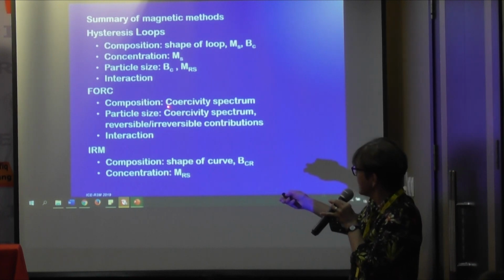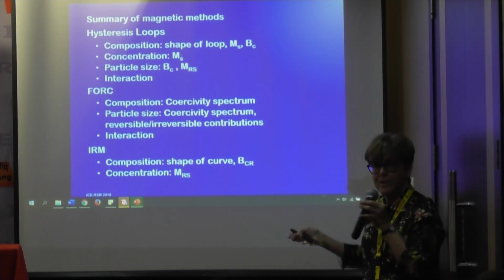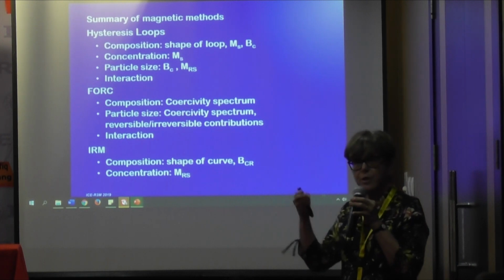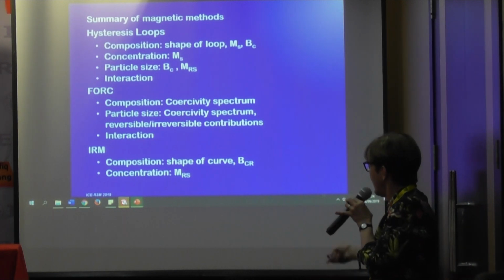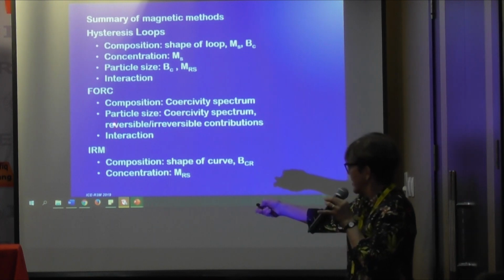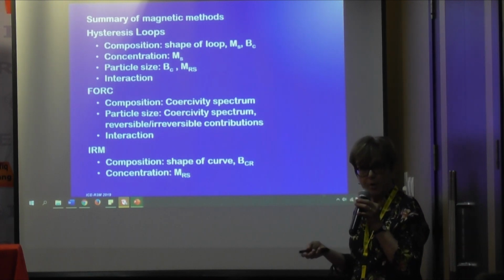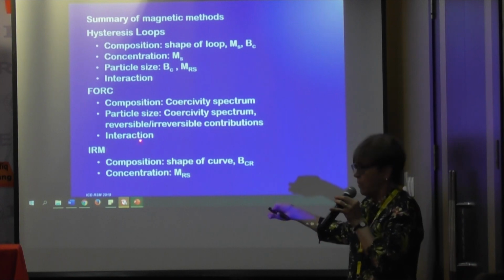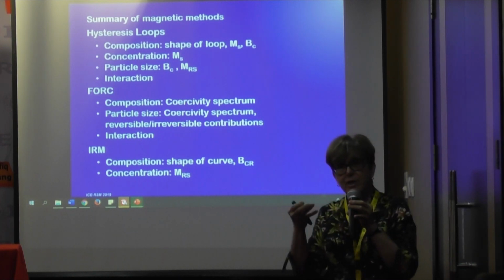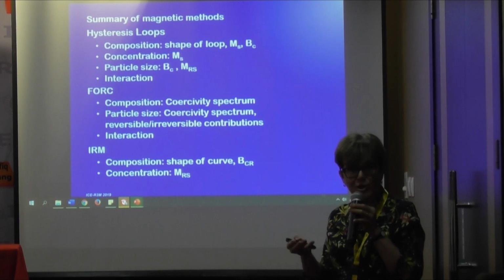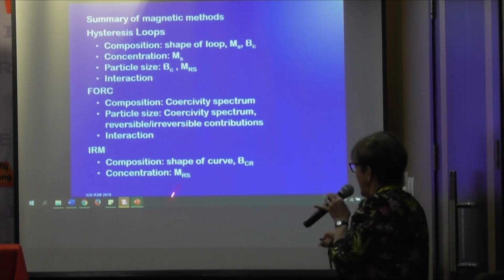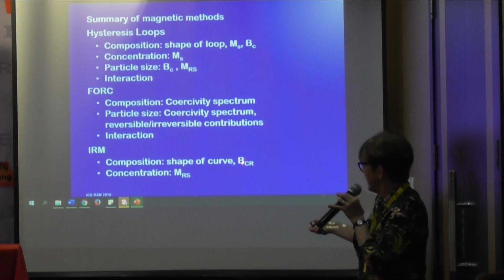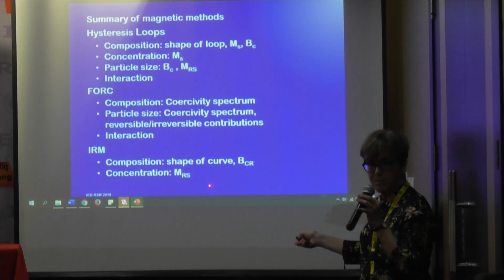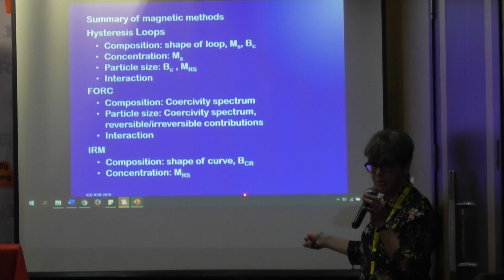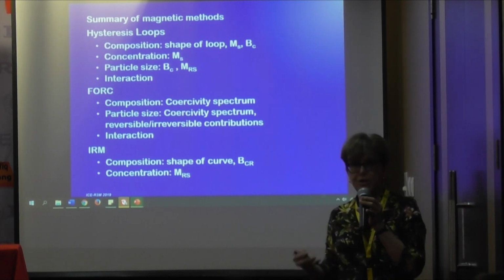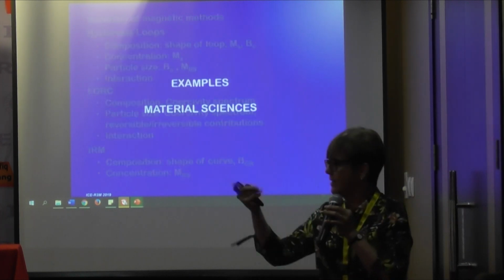In FORC diagrams, the coercivity spectrum is going to tell us something about composition and also about particle size. And we can also get that from this reversible, irreversible part of the sample. But what's nice about FORC is we also get more direct information about interaction between particles. And with the IRM method, we get information on composition from the shape of the curve and also from the remanent coercivity, and we get concentration from the remanent saturation.